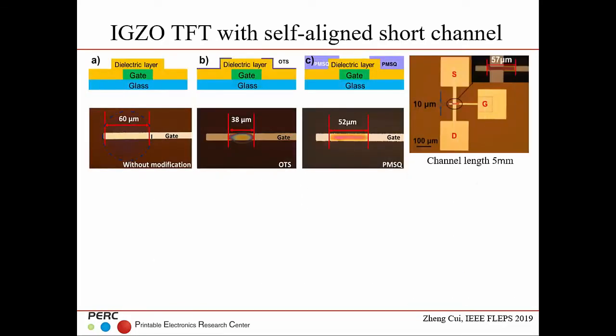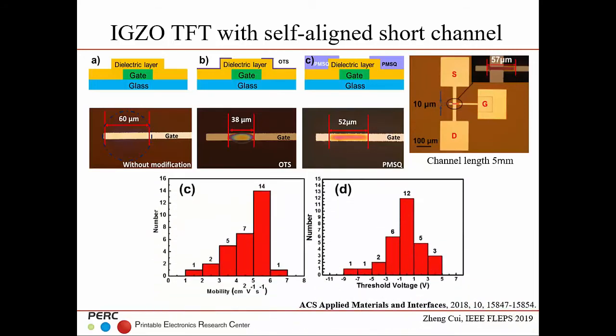And we also work on the metal oxide, and for the metal oxide, we focus on IGZO. This graph shows that we use a self-aligned process in which we inkjet print the metal oxide ink. It allows the ink to be distributed only between the source and drain electrodes, because we make both sides hydrophobic and only the channel hydrophilic, so the ink can be concentrated on that channel. And we get good mobilities and threshold voltage, and these work truly like transistors.